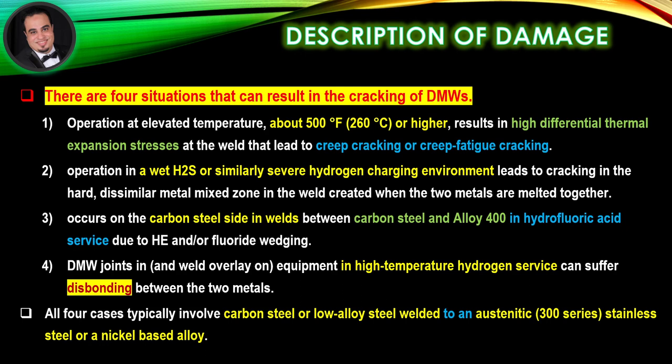The third situation occurs on the carbon steel side in welds between carbon steel and alloy 400 in hydrofluoric acid service, due to hydrogen embrittlement and/or fluoride wedging.